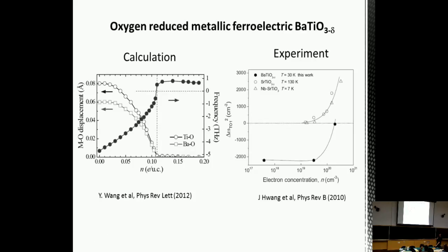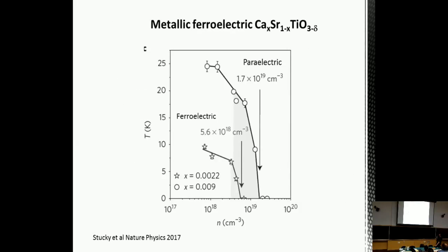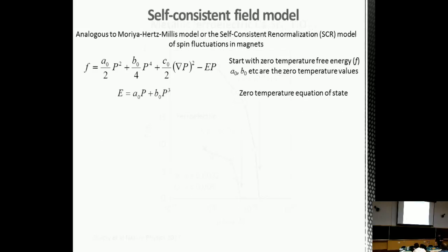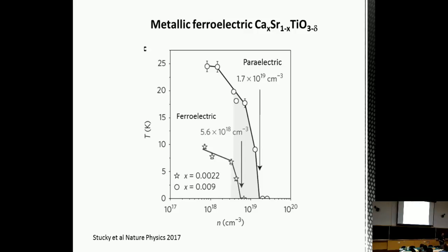Yeah, so here's a case where you can tune through the quantum critical point into the ferroelectric phase by calcium substitution. This curve here shows the ferroelectric phase transition temperature being suppressed to 0 with carrier concentration. And in these cases, the superconductivity appears right the way through, and it's not really been tested out properly, but it seems to show that there's a peak around the ferroelectric phase transition. And that's also been done with oxygen-18 isotope tuning as well.